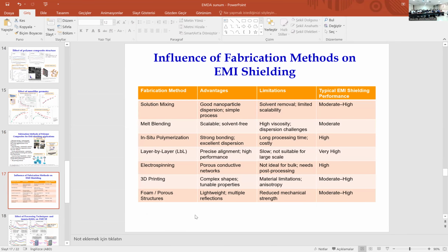This table compares the different fabrication methods used for polymer-based EMI shielding materials and highlights how the processing controls the final performance of the materials. Methods such as in-situ polymerization and layer-by-layer assembly provide superior dispersion and filler alignment, resulting in higher shielding effectiveness. In contrast, scalable techniques like melt blending offer easier manufacturing but generally yield moderate EMI shielding performance due to their limited nanoscale control. This table shows that the balance between process complexity, filler distribution, and structural precision determines the shielding quality of the polymer composites.